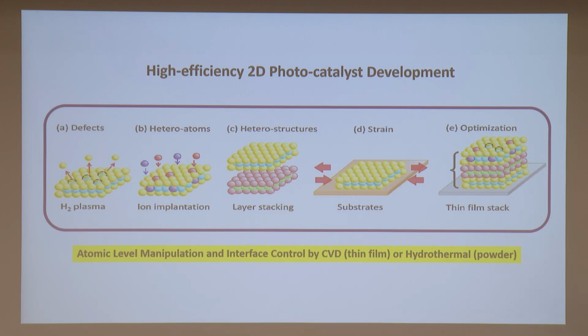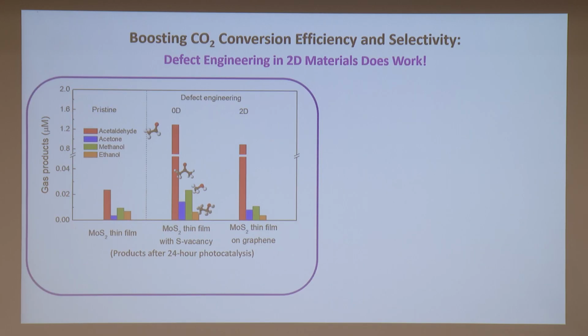So the essence is to reach atomic-level manipulation and also control the interface, either by the CVD method or by hydrothermal in the powder. Okay. So this is the end result of defect engineering in 2D material. And it does work in this sense that if you do only the pristine thin film, and do the gas product analysis by GC, you'll see there are quite a lot of products, but they are all very small, almost within the error bars of the detection limit.